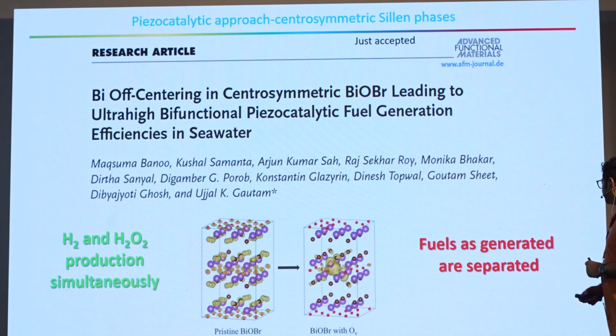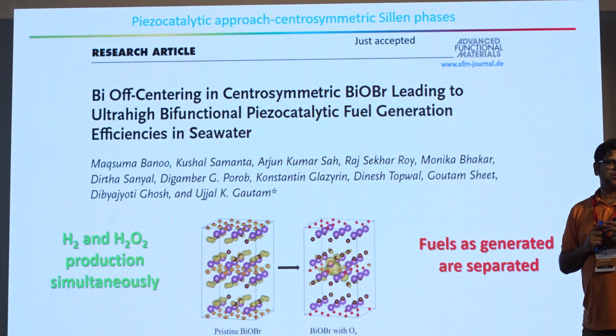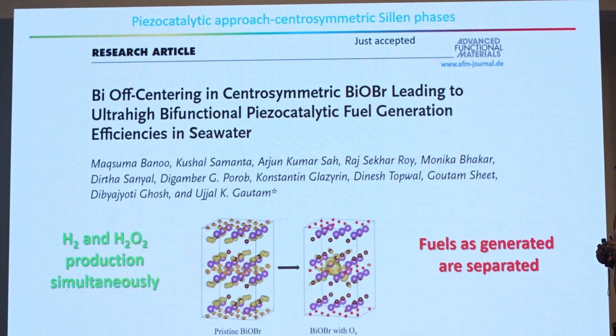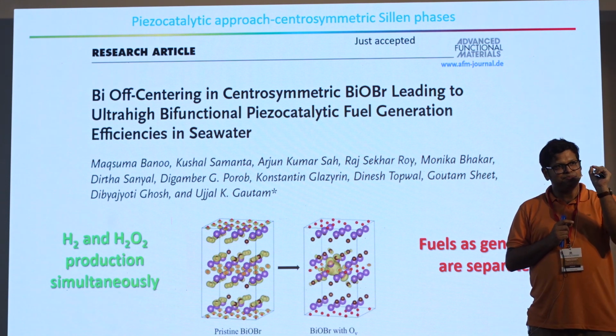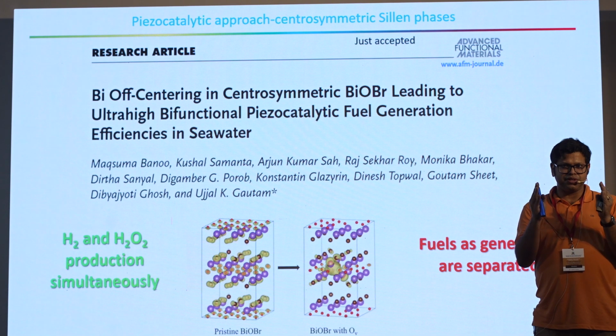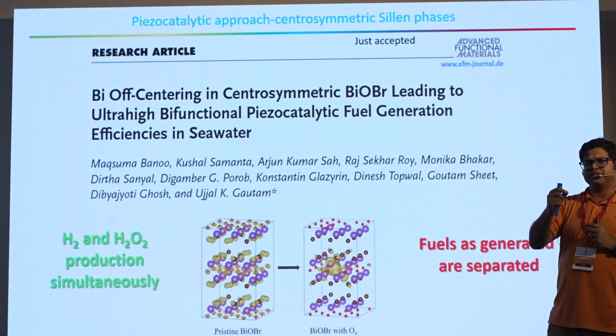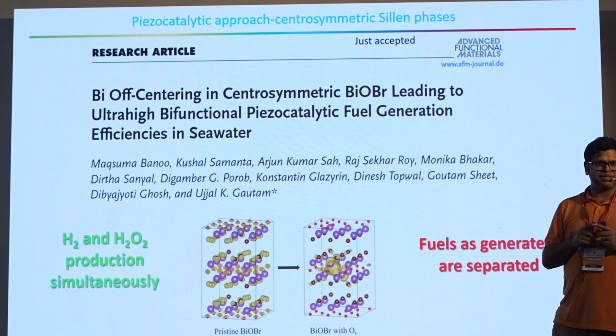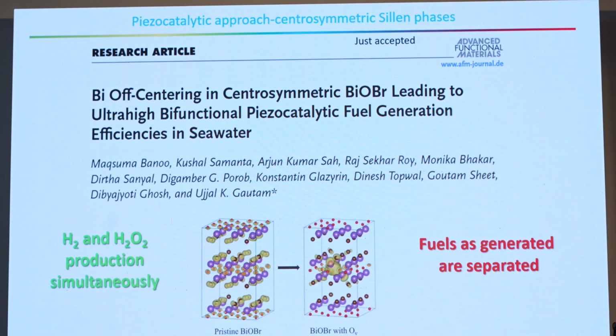The other reason why this paper is important is that we have positive charges and negative charges. The negative charges give rise to hydrogen because they react with a proton. The positive charges give rise to oxygen, which is not very useful. In this work, for the first time we saw that we can get hydrogen and hydrogen peroxide on two sides of the crystal. So you see now we have two fuels getting generated at the same time. Another important point: when you produce hydrogen and oxygen, you have to separate them if you want to use hydrogen. In this case, because hydrogen peroxide remains in the solution, you do not have the problem of separation. So you have two fuels generating at the same time, but you do not have to separate them.